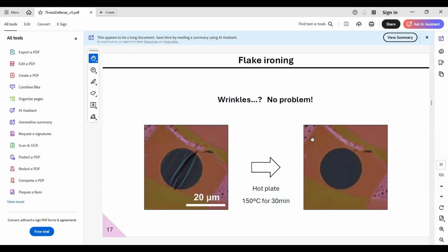So which material is this for, all your TMDs or just for molybdenum selenide? I mean, we prepared suspended samples of other materials, but not specifically this one. And these wrinkles don't occur in every transfer. So I cannot tell you if it's material specific. I can tell you that it does not always work. Yeah, no, I understand that part. But the reason I ask is because I know the selenides tend to be more sensitive to air than the sulfides. So if this was molybdenum selenide or tungsten selenide and you heat it up in air, I'm just wondering if you slightly oxidized it.